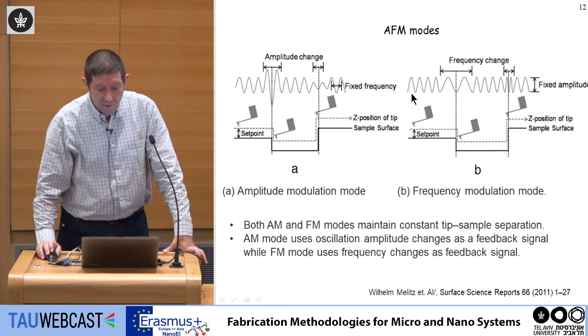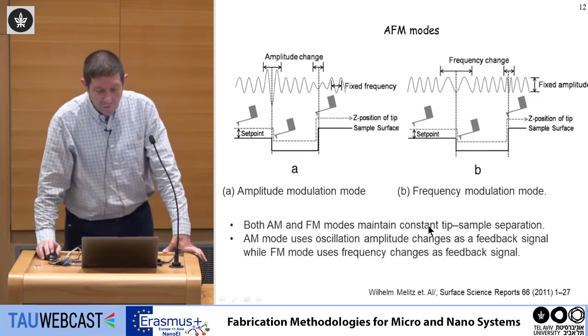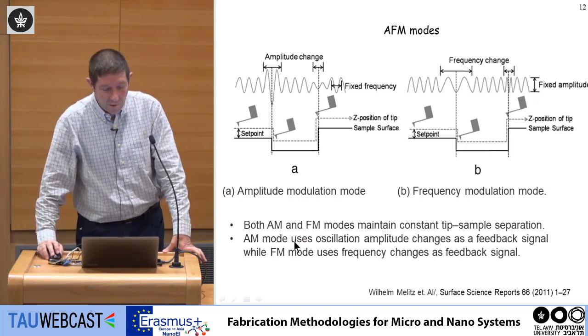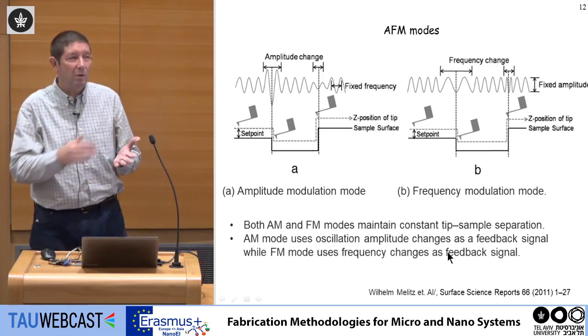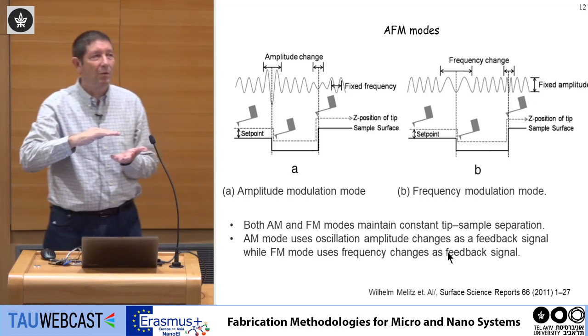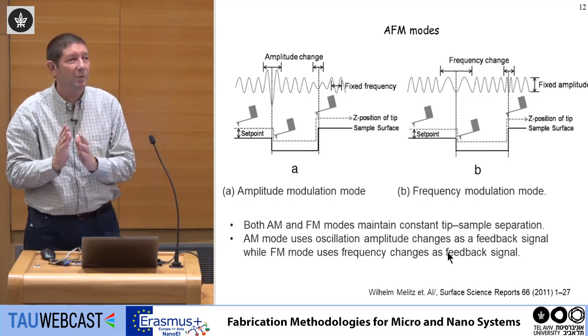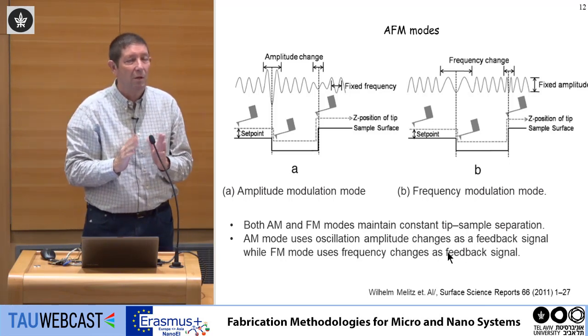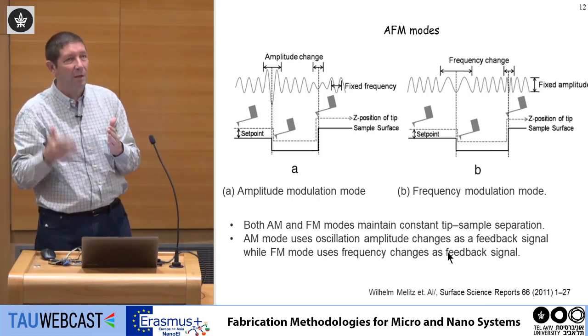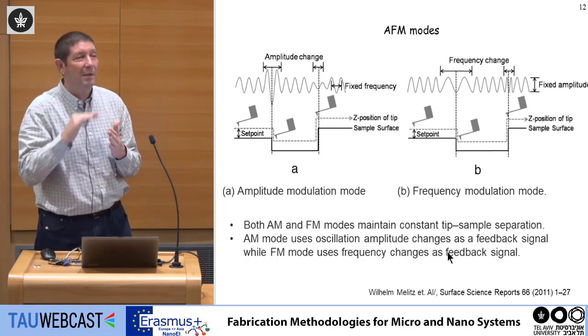In this case, this is like a set point, and when you are modulating the frequency and go over a step, you see a frequency change, and the amplitude is fixed here. So both AM and FM modes maintain constant tip sample separation. AM mode uses oscillation amplitude changes as the feedback, while FM mode uses the frequency change as the feedback. What you're doing, you're scanning and vibrating, and feedback means you want to maintain a constant frequency or a constant amplitude. So whenever there is a change in amplitude, you apply a feedback, and your signal is the feedback, how to maintain the fixed signal.